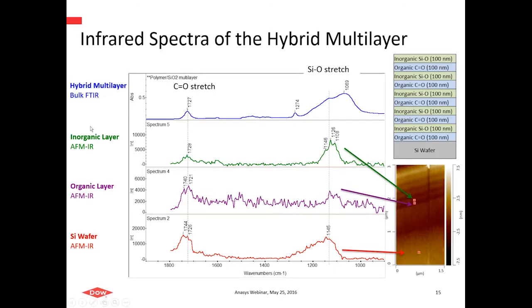So if we start again with a bulk analysis of this stack, we can do ATR from the top, so with ATR crystal at the top of the stack. And we see components of both polymers in this full spectrum. We see a carbonyl stretch at 1729 wave numbers, and then this SiO stretch at lower wave number. And we can again put the probe down in alternate layers and collect a spectrum in alternate layers based on this height image inset. And we see in one case we must be on the inorganic layer because we're seeing a strong response for this SiO stretch. And in the adjacent layer we see a stronger response in the carbonyl region. So clearly again we can identify which layer is which.